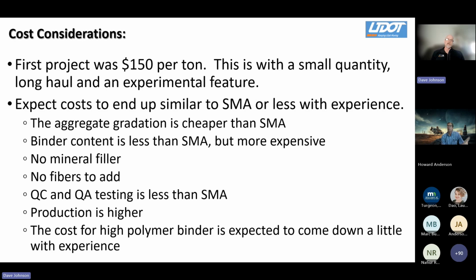We expected the binder content to be less than what was required for an SMA, but because of that high polymer, thought it would be a bit more expensive. We didn't anticipate the need for anything like mineral fillers or fibers. We figured that the testing would be slightly less for both QC and QA than what it was for SMAs. We thought that we could produce this at a higher volume, and we did expect that with time, the cost of the polymer would become more cost competitive as it moved to be more of an everyday mix in the state of Utah.